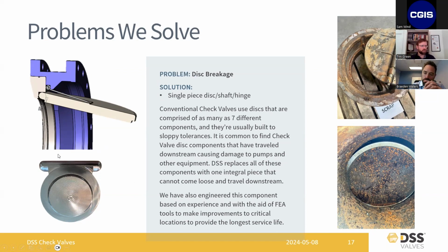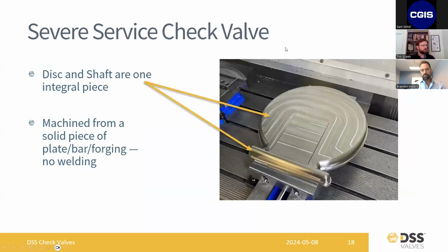So our single piece disc replaces 6 or 7 different components that are prone to breaking on these styles of valves. The hinge is integral with it. There's no welding in this location, so it's a very strong component. These valves are designed to give years and years of repeatable function without fail. This is a 16-inch stainless steel disc being 3D milled out of a solid piece of stainless steel plate. Again, no welding. This is probably the most critical location. We put a nice radius on all of them here for added strength, and no welding, all one solid integral piece.